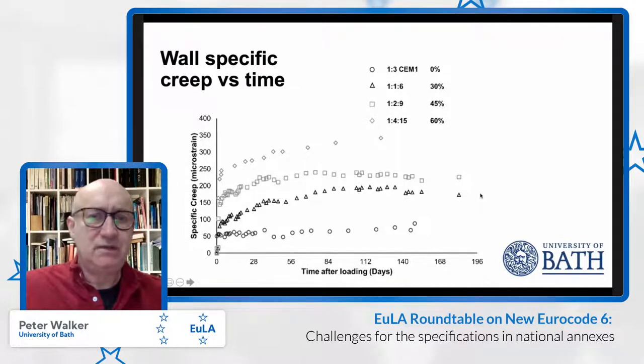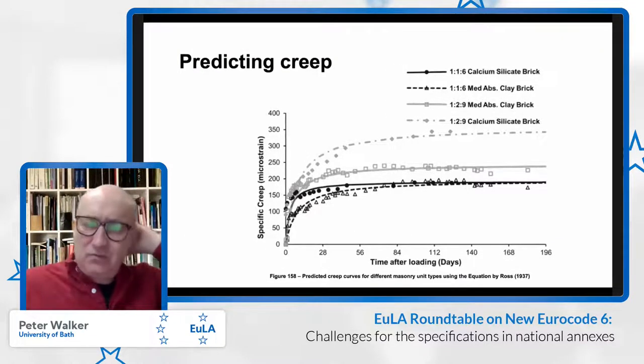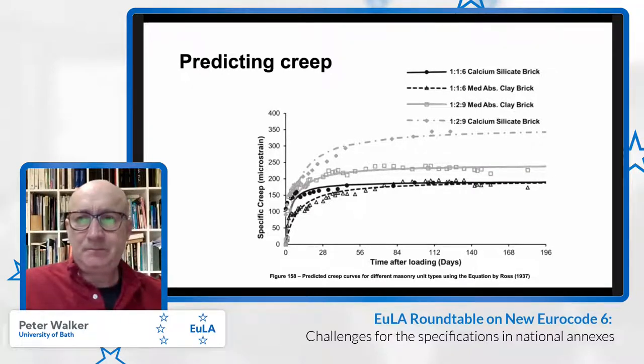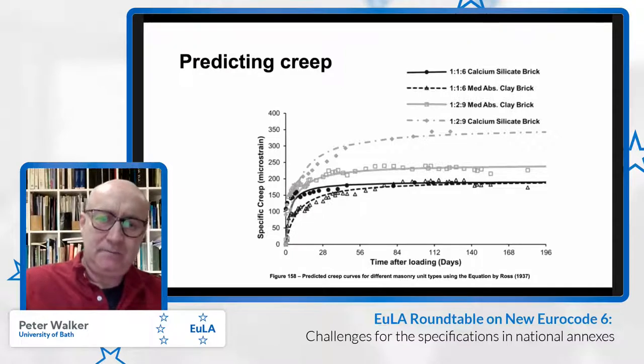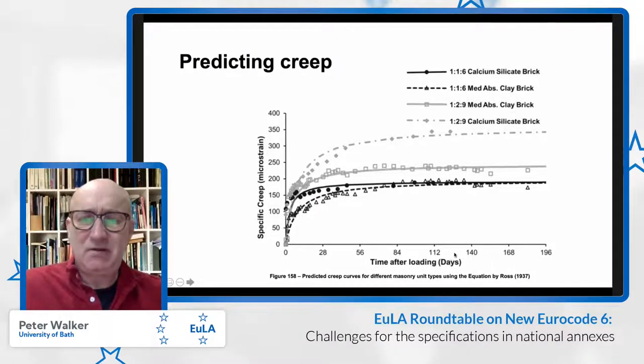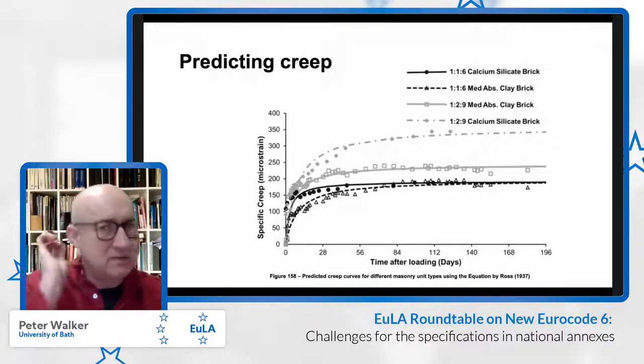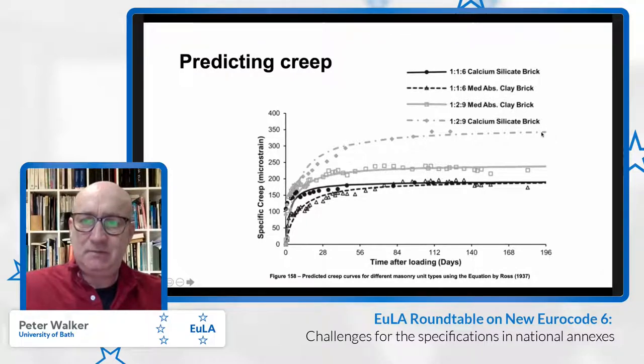of these materials. As part of the research, I'm almost coming to the end of my presentation, we did look at ways of predicting creep, and we compared the measured creep with the predicted values from the current Eurocode 6 guidance. And we also looked at it empirically, predicted by an equation originally developed by Ross in 1937, which has been also developed for use in concrete and cement materials. And you can see the predicted values here.